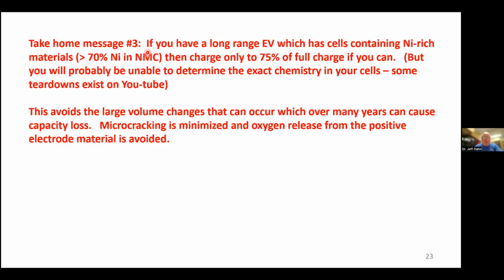So take-home message number 3 is, if you have a long-range EV which has cells containing nickel-rich materials greater than 70% nickel, then charge only to 75% of full charge if you can. But you may not be able to determine the exact chemistry in your cells. Turns out that on YouTube, there's teardowns, and maybe people will take apart the cells in your car and do all sorts of chemistry to figure out what the positive electrode material is. And doing this avoids the large volume changes that can occur, which over many years can cause capacity loss, microcracking is minimized, and oxygen release from the positive electrode materials avoided.